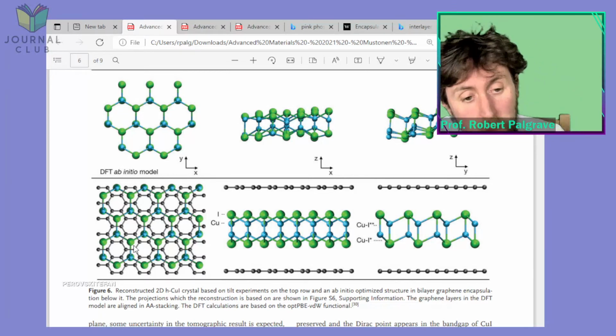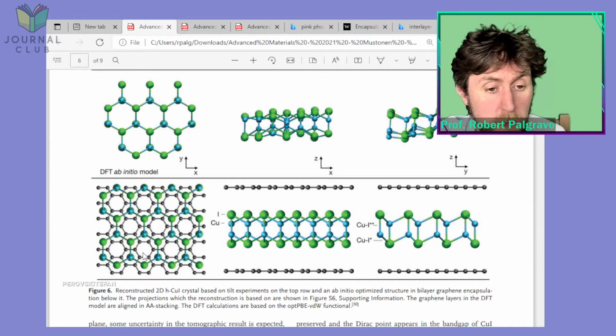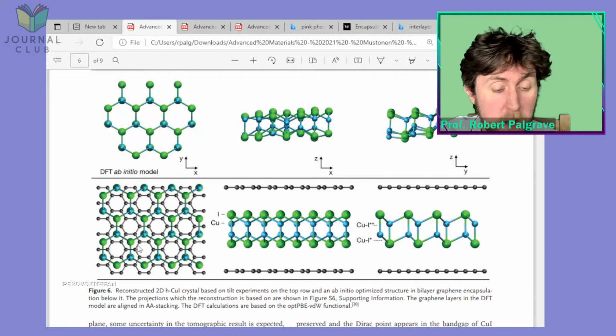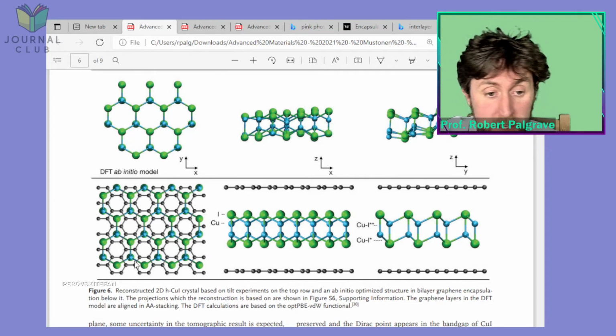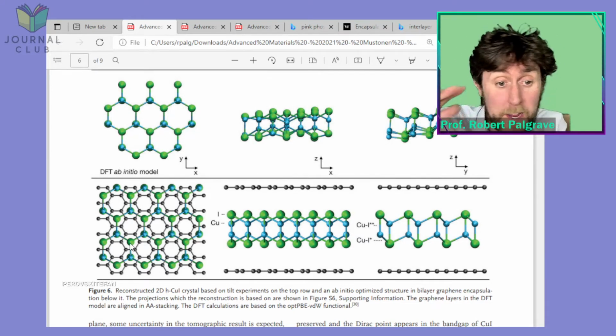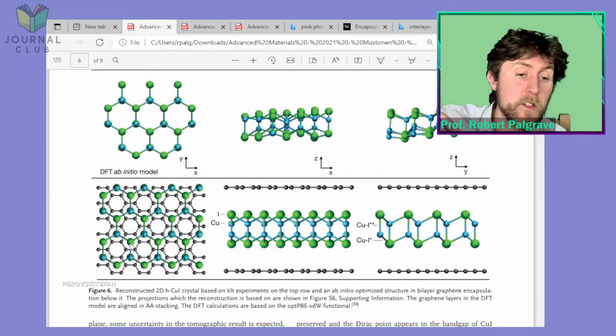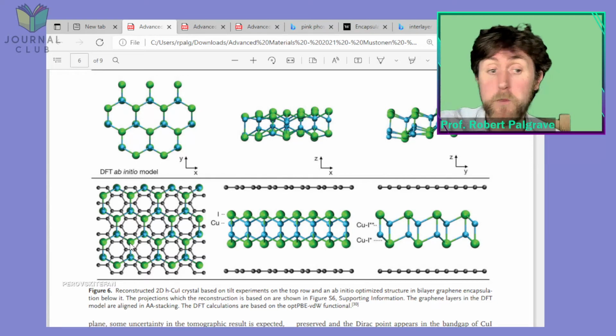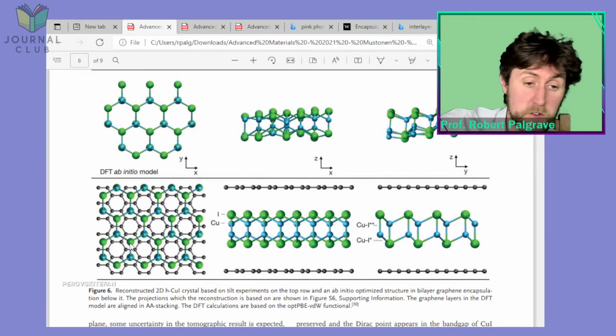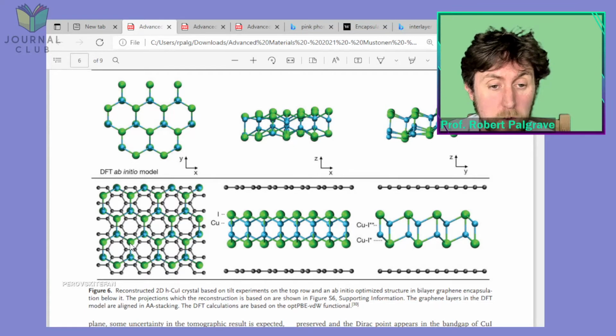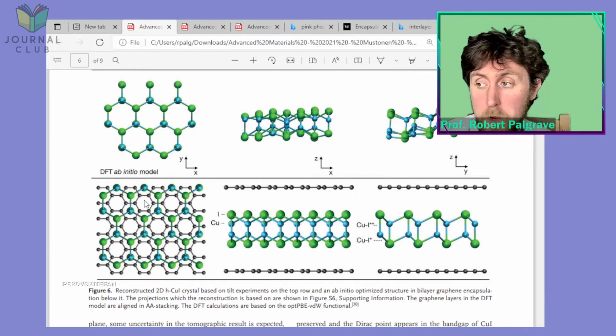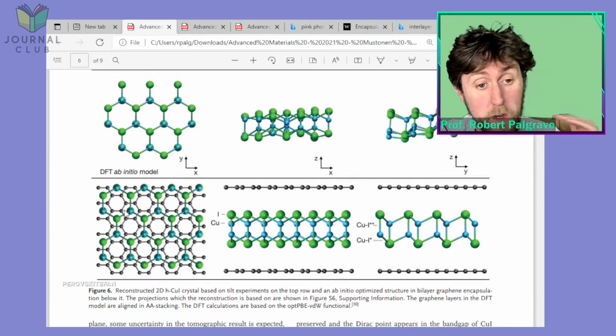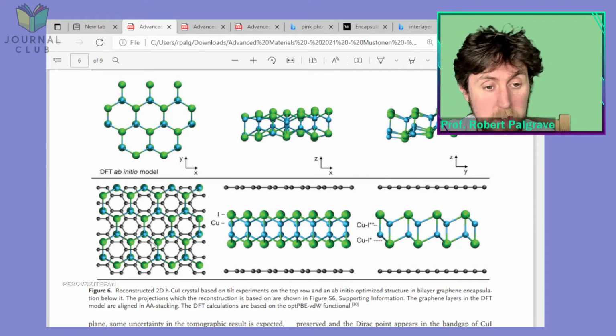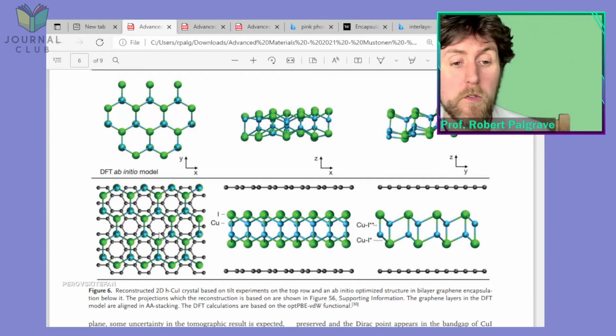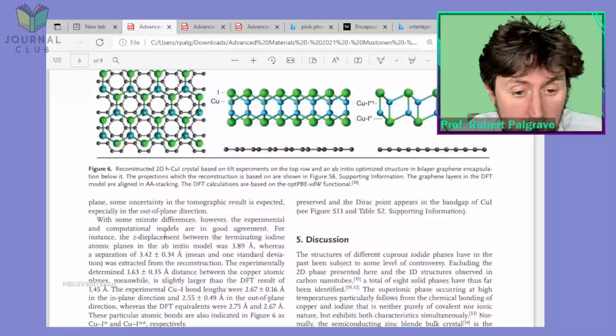So I think the reason this actually works is probably that these two lattices, the cuprous iodide and the graphene, have this simple relationship. You could call it an epitaxial relationship almost, like the way you can epitaxially stabilize thin film materials on top of a particular crystal structure substrate. Maybe that's what's at play here: because the graphene has this hexagonal structure, they're able to stabilize this hexagonal cuprous iodide structure.